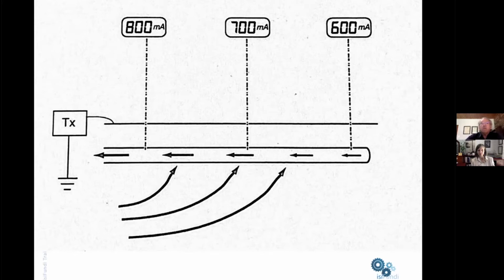So we have a transmitter which injects a signal into the pipeline, and then we have a receiver which can measure the magnitude of the current that is injected into the pipeline. Now, the PCM stands out because the signal that it injects is a very, very low frequency signal, something like 4 hertz. And it tends to behave very much like the DC that we get from a cathodic protection system. And the beauty of this operation is that you can follow the current using a non-contact method, and you can also get a good idea of what's going to happen with your cathodic protection current.